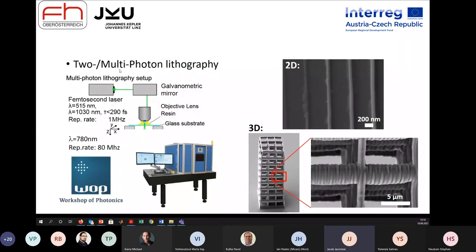Good. With this, our system is custom made by Workshop of Photonics. We have designed it, and they built it up for us. We have basically two wavelengths that we typically operate: a 515 nanometer femtosecond pulsed laser and at 1030 nanometers a femtosecond pulsed laser, so it's a frequency doubled laser. We have a pulse duration of around 300 femtoseconds, and the repetition rate is 1 megahertz.